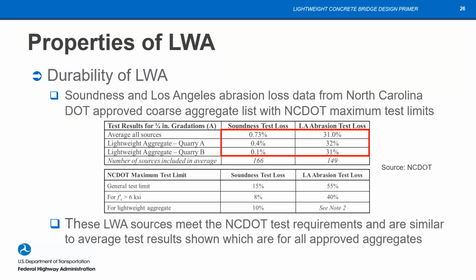What about the durability of lightweight aggregate? Here are some test results from the approved aggregate list for North Carolina DOT. Since that's where I live, I was looking at these. The average for all sources for the soundness loss test is 0.73%. And then here we have two lightweight aggregate supplies, quarries. They are located on the same source material at different locations, but they have very similar properties. Here you can see that these losses due to soundness are significantly less than the average of the normal weight aggregates, and well below the requirements that NCDOT has for the test loss.